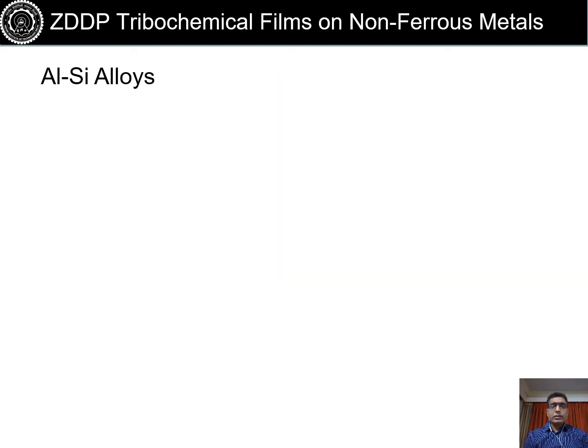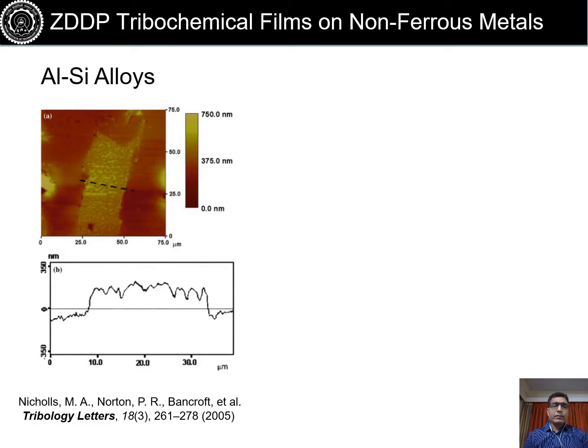So before I share the results, I will show what people have seen on these alloys in terms of formation of these films. It has been observed in macro scale experiments that mostly silicon phase is where the tribofilm develops, and ZDDP forms a nice thick protective layer on silicon phase, but aluminum matrix doesn't seem to support these films. But the reason is not very clear because of the complexity of the macro scale sliding interface. A lot of wear is generated in macro scale experiment. Then there is a lot of mechanical mixing. So a lot of damage happens to the interface, which makes it hard to interpret the results.